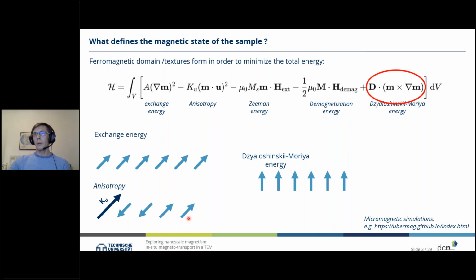Then we have something very important for modern materials, which are skyrmions and anti-skyrmions, which is the so-called Dzyaloshinskii-Moriya energy, or Dzyaloshinskii-Moriya interaction, DMI for short. This is an energy which favors perpendicular aligned magnetic moments, which you see here by the cross product of the magnetization and the gradient of the magnetization, multiplied by the Dzyaloshinskii-Moriya interaction constant. If we again take a starting configuration like that and minimize the energy, we will end up with a magnetic configuration which looks like that. The magnetic moments try to align perpendicular to each other in order to minimize energy.